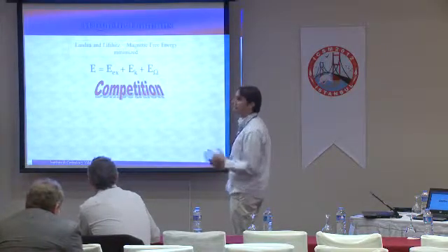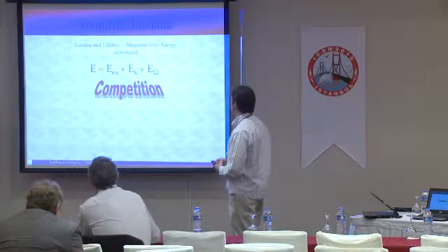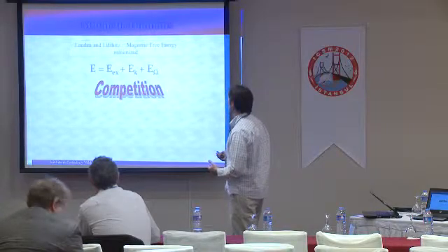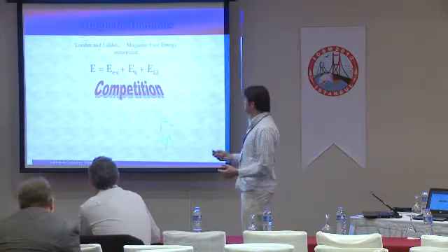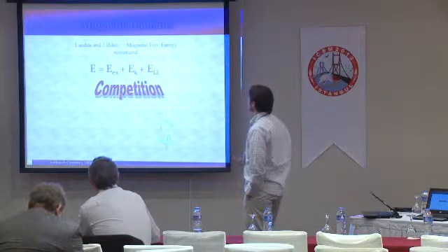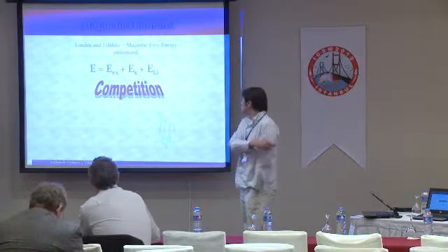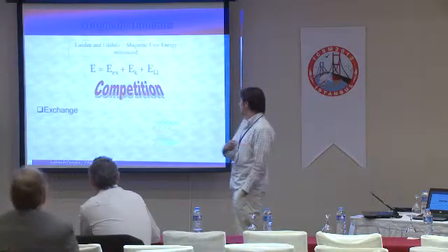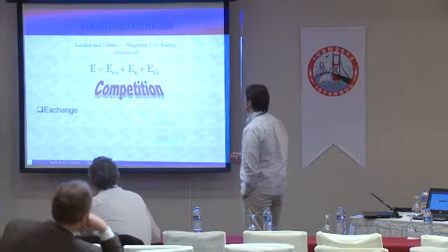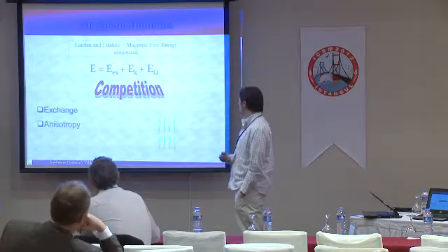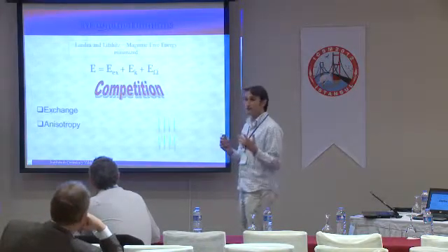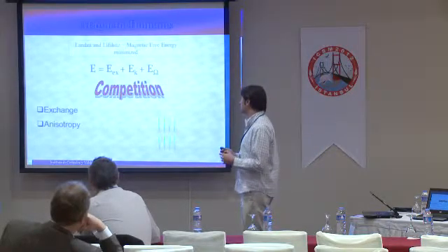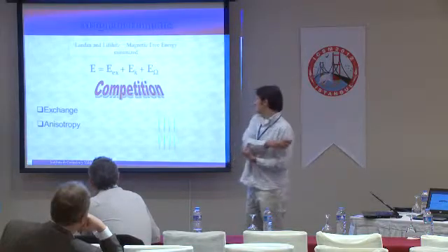I'm only going to focus on these three for the sake of simplicity, but there are a couple more. Basically, the first one here, the exchange interaction, consists of, when you have a system of spins, the exchange interaction is going to align them parallel to one another. But if one only had this interaction, then they would be aligned randomly in any direction in space. The second term here, the anisotropy term, is going to favor specific crystal orientations of the alignment, usually due to the spin-orbit coupling to the crystal lattice, as you know.